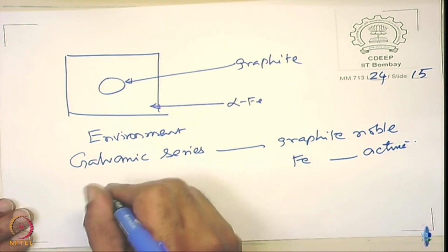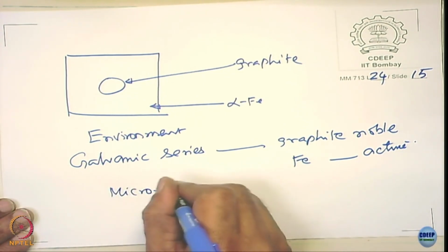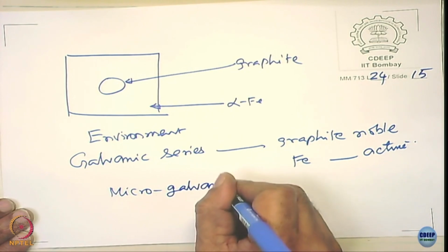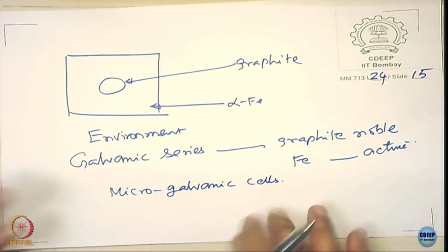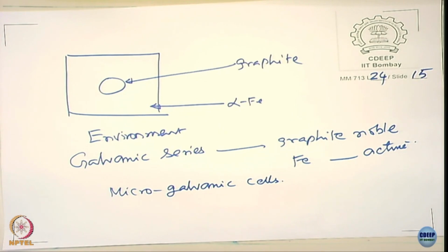So, what is going to happen? You are going to have micro galvanic cells. It is not a typical dealloying like what you see in your brass or maybe in cupro-nickel alloy system. Here there is a distinct graphite phase and there is a distinct matrix of alpha iron, and so they have different noble and active characteristics, and the one which is noble will act as a cathode, the one which is active will be suffering corrosion, actually serious corrosion here.